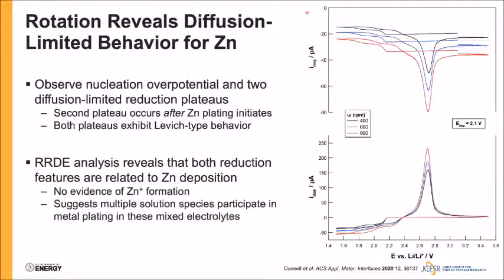I won't show it here, but if we do a corresponding experiment where we hold the ring electrode at very positive potentials, we don't see any evidence of reoxidation of a solution species such as a monovalent zinc ion. So we don't really see any evidence of Zn+ formation. So what the voltammetry tells us is that there are multiple solution species that are leading to the deposition of zinc metal in this system.